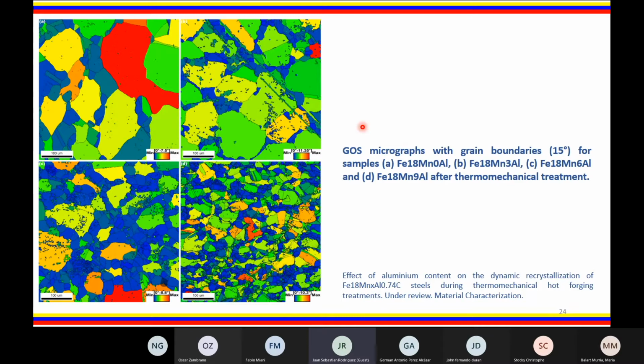On the other hand, the figure corresponding to the grain orientation spread of these alloys is presented. It is interesting to observe that the degree of misorientation of these is low, which coincides with the previous work and indicates that the grains are newly formed by the hot forging process. In addition, the formation of the necklace structure is also appreciated, which is a clear indication that this process occurred through continuous dynamic recrystallization. Something quite interesting to appreciate is that increasing the aluminum content of these alloys generates a grain refinement. We will delve into this later.